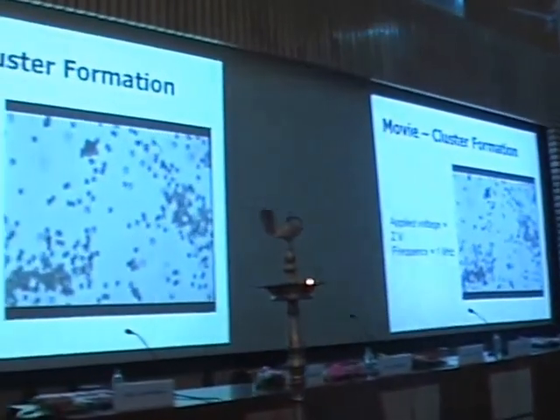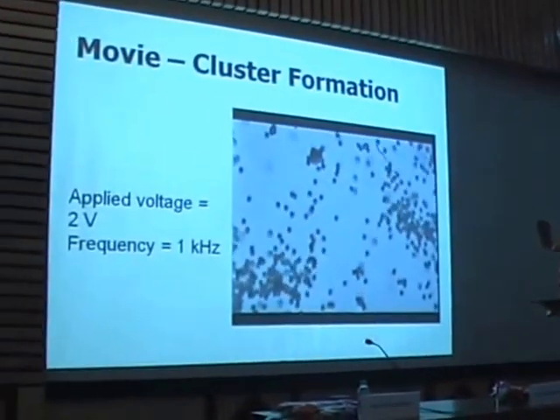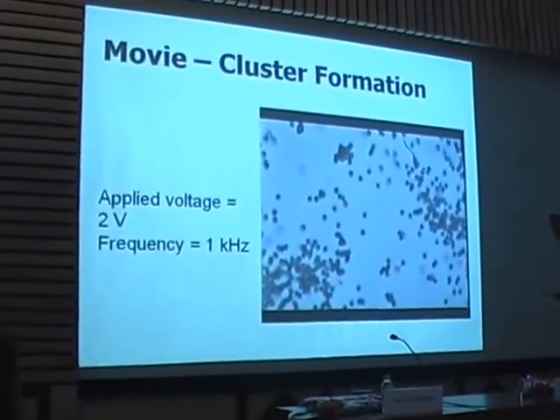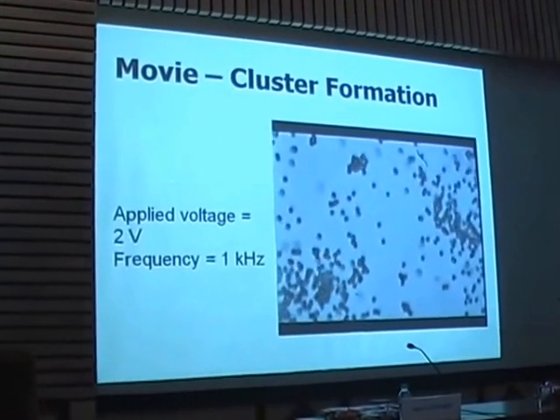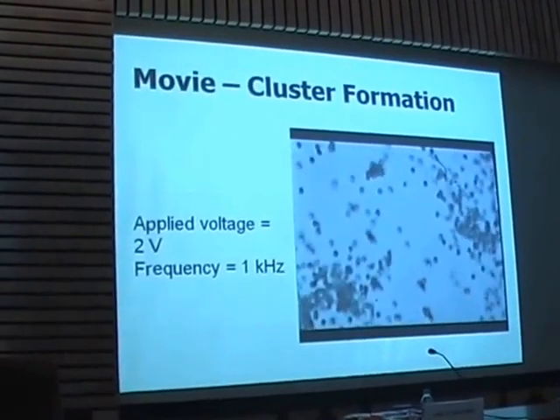And this is something which we studied, and you can form these beautiful crystals when you put the electric field. So, for example, you apply a voltage of 2 volts on these two plates, at 1 kilohertz, and after some time they will all come together and form a crystal. So this is crystallization under electric field in the xy direction.